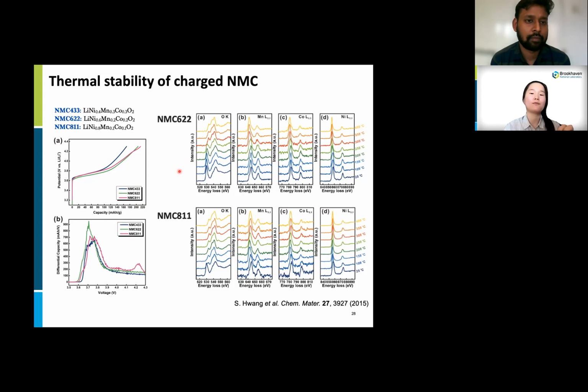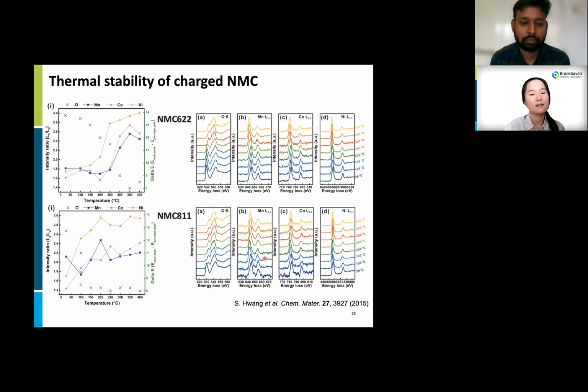I increased the temperature of the 2 compounds and collected EELS spectra at every 50 degrees C to see the thermal stability of these 2 compounds. These EELS spectra are summarized in the graph on the left. In the case of NMC811, the features in the oxygen K-edge and transition metal L-edges change dramatically around 100 degrees C, but these kinds of changes happened at much higher temperature in the 622 composition, which means NMC622 exhibits better thermal stability.